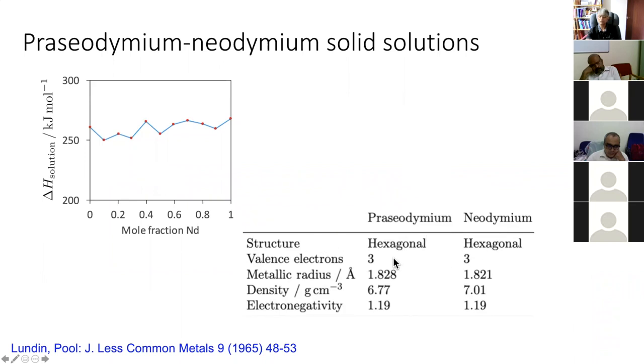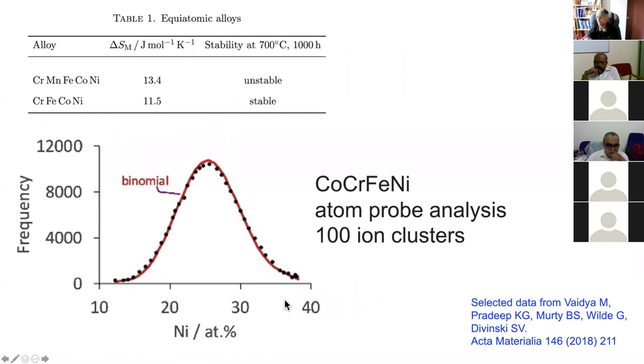They both have the hexagonal structure, both have the same number of valence electrons, roughly the same atomic radius and the same electronegativity. So when you make different mixtures of praseodymium and neodymium, the heat of solution remains constant. What that means is that the enthalpy of mixing is zero. These are experimental measurements of the heat of solution of one of these in the other. So this is a very rare example of what would be an ideal solution at equilibrium. All right. The previous data that I showed you, I emphasized that this may not be at equilibrium because the same experiment needs to be done after holding at 700 degrees centigrade for a very long time.